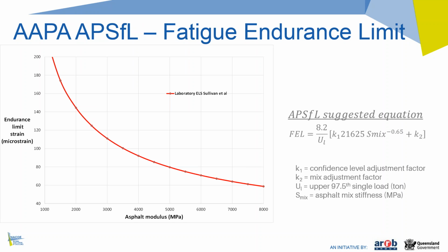This slide basically shows the fatigue endurance limit that is proposed by the APA method. And in short, the design is to come up with different asphalt thicknesses such that when we are evaluating at the winter, summer, or the WMAPT temperatures, the calculated critical strain at the bottom of the asphalt is lower than this proposed fatigue endurance limit, and the method suggests that if that is achieved, then we will have a very long life pavement.